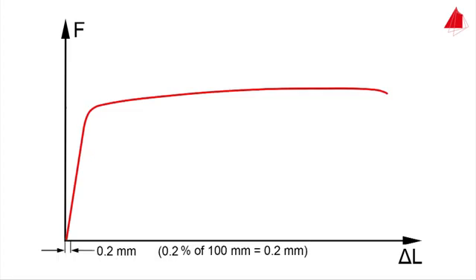And this is the way to calculate it. First of all, the elongation that corresponds to 0.2 percent of strain has to be computed. For an initial gauge length of 100 millimeters, the result is 0.2 millimeters.